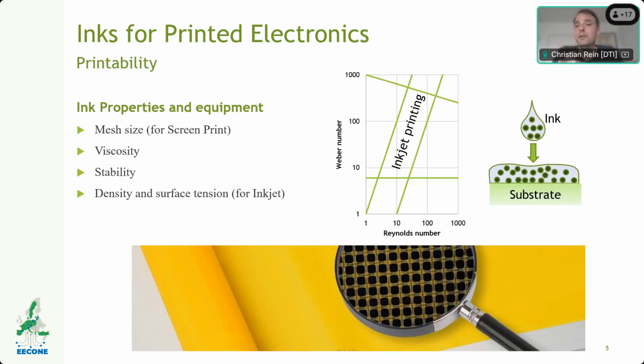These inks, depending on the methods of deposition, need to account for several parameters. If you are taking, for example, screen printing, which is a very robust, established method for printing electronics, then you need to take into account the mesh size. As you can see in the picture, the mesh through which you put the ink is made up of a lot of pores through which the material has to go. It also depends on viscosity and stability. And for example, for inkjet, you would also take into account density and surface tension in order to have the right flow dynamics. Then there would also be a similar consideration if you're doing roll-to-roll production for upscaled production.